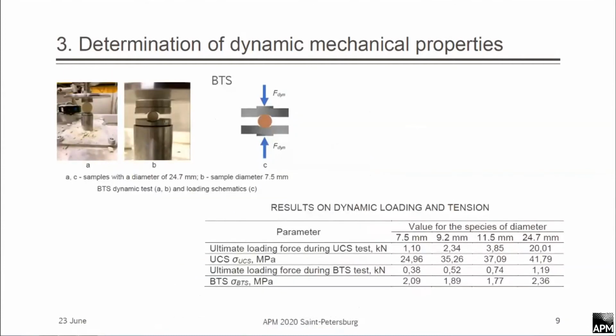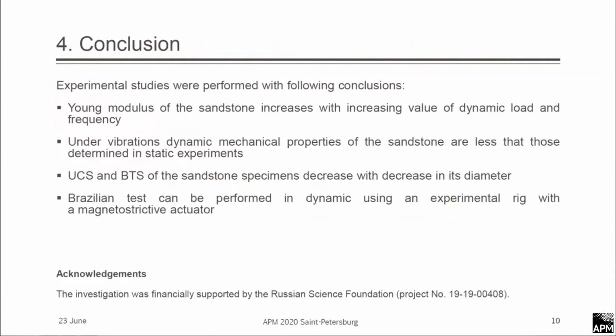So then, as we settled all the installation, we determined dynamic mechanical properties, and particularly we applied the Brazilian methodology for testing and determining tensile strength in dynamics. And here you may see the results which we obtained: Brazilian tensile strength versus uniaxial compressive strength.